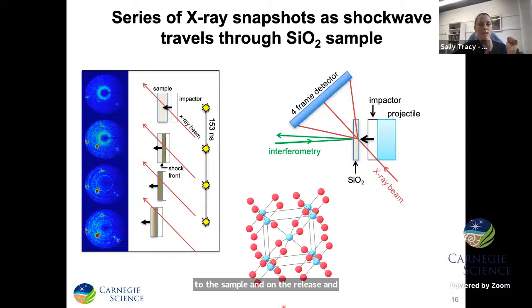And so on the left, this figure shows results from an experiment where, in this case, we shocked silica glass to a pressure of around 50 GPa or so. Here, this first image corresponds to a frame that was collected just prior to impact. The second 2 images are diffraction patterns, or X-ray images, that were collected as the shock wave traveled through the sample. And then the final image here was collected right after the shock wave reached the sample rear surface. And so we're starting to see a release wave come back into the material. From this data, what's clear is that for the first time, we're able to say that the high pressure phase that forms under this type of dynamic loading condition appears to be a 6-coordinated crystal structure.